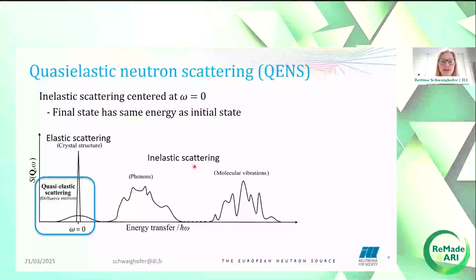Now that we've established these basic terms for neutron scattering, we can start talking about quasielastic neutron scattering. QENS is an inelastic scattering that is centered at zero energy transfer. It is associated with diffusional behavior and occurs due to processes with a distribution of energies, where the final state has the same energy as the initial state. QENS can be used to study dynamic processes like rotations and translations.